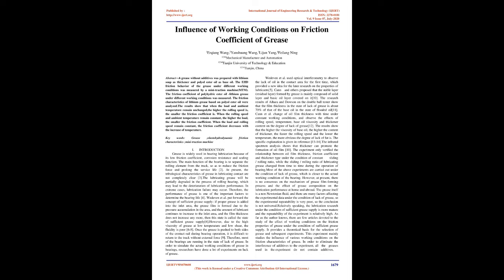However, due to the high viscosity of grease at low temperature and low shear, the fluidity is poor 6 to 8. Once the grease is pushed to both sides of the contact track during bearing operation, it is difficult to return to the track without external force 9. Therefore, most of the bearings are running in the state of lack of grease. In order to simulate the actual working conditions of grease in bearings, researchers have done a lot of experiments on lack of grease.